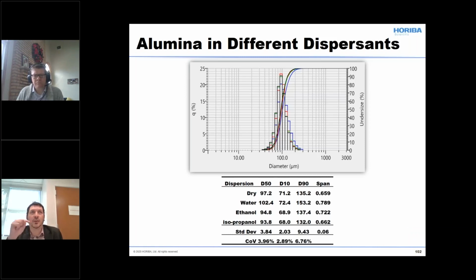And it's clear when you're measuring the sample. Laser diffraction lets you put the sample on the wet system once, and then you have sample circulation. You can take as many measurements as you want, and they should be extremely repeatable, because you have the same set of particles running through the system. If you see the results jumping and you have some bumps on the shoulders, they're not consistent at all, it means your particles are not well dispersed. You may have the right dispersion medium, but you may be lacking a surfactant.